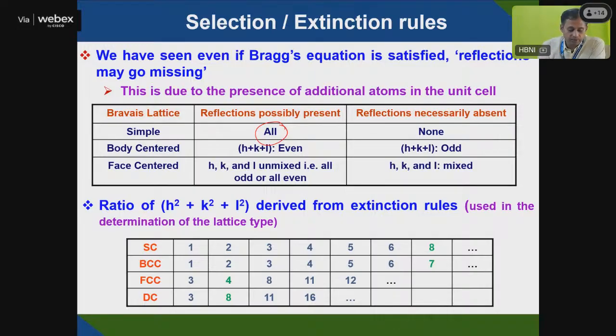But in the body centered cubic, the BCC structure, H plus K plus L has to be even. In the case of face centered, H, K, L must be unmixed, all even or all odd, then only will you be able to see a diffraction peak. That means you can derive the ratio of H square plus K square plus L square. Based on the extinction rules, you can determine whether it is FCC, BCC, simple cubic, hexagonal, or diamond structure. In a simple cubic, H square plus K square plus L square can be 1, 2, 3. But in BCC, it is like 2, 4, 6, 8. Here it is different.